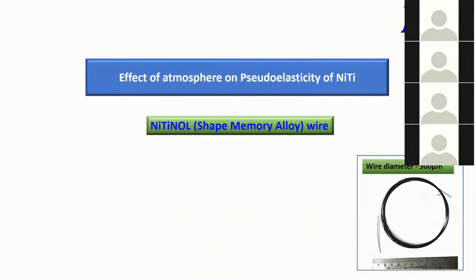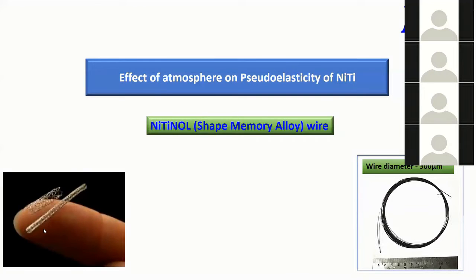So we focus much more on the pseudo-elastic properties of nickel titanium. And we work on different categories of nickel titanium and in different forms. So this work here is focused on the wire. It has a very thin diameter of 300 micrometer, very thin. And you see that when we use these as stents, or in orthodontic archwires, we use wires of very fine dimension. So that's why our work focused on the wire to evaluate the properties.